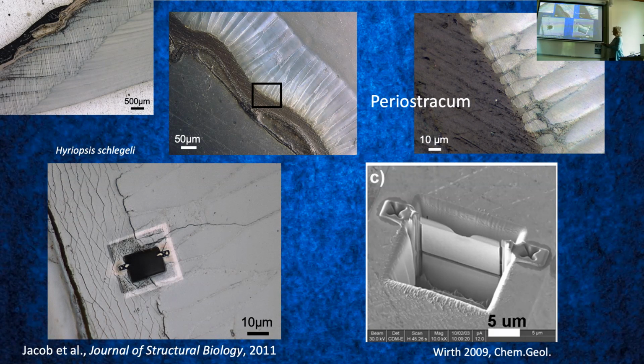In this case, we did this with one of the shells. This is the section of the shell. This is the aragonite, the nacre part of it. So we found an area of interest here, close to the outer layer on the shell, which is organic. This is from a publication of the guys I did this with. Basically you have a gallium ion beam that digs a hole. These crosses are here to correct for the drift in the SEM while you cut, because otherwise you're never getting that foil out of that ditch. Then you cut a ditch in front and behind, and you're left with a little foil that you can cut out and lift out, and you can use this for analysis.